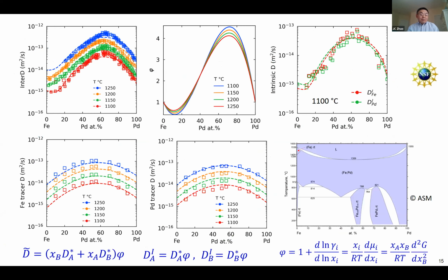So this is an example of the iron palladium. You can see that this is the interdiffusion coefficient at 4 different temperatures. This is the thermodynamic factor. As I mentioned, when you have an ordered phase, delta H on this side is negative. This side you have a small miscibility gap, so that the delta H mix is positive. So you can see that if the elements do not like each other, in this case, it decelerates the diffusion. This side, they like each other, you have an attraction to accelerate the diffusion. That's the beauty of the Darken equation.